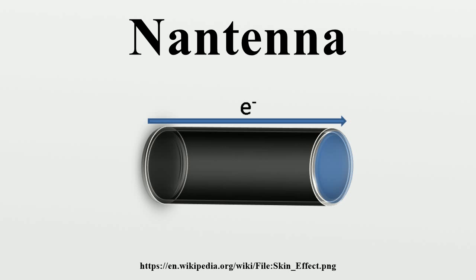To improve the efficiency of carbon nanotube-based rectenna: Low work function. A large work function difference between the MWCNT and the top electrode is needed to maximize diode asymmetry, which lowers the turn-on voltage required to induce a photoresponse. The work function of carbon nanotubes is 5 electron volts and the work function of the calcium top layer is 2.9 electron volts, giving a total work function difference of 2.1 electron volts for the MIM diode.